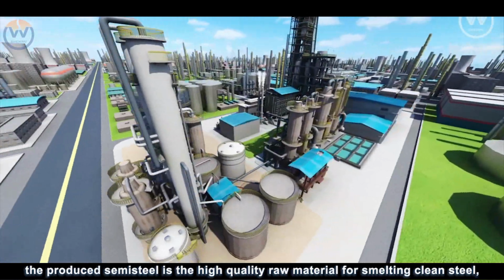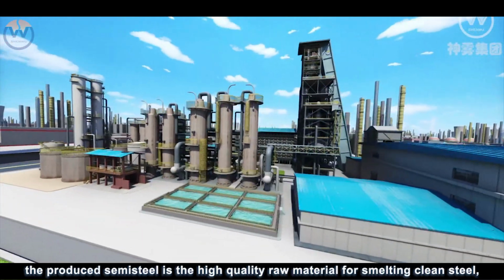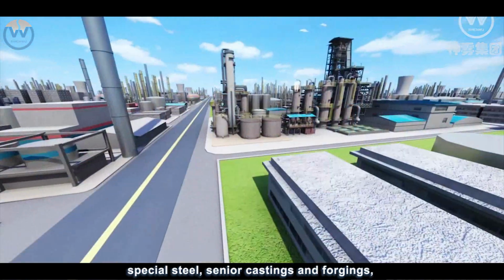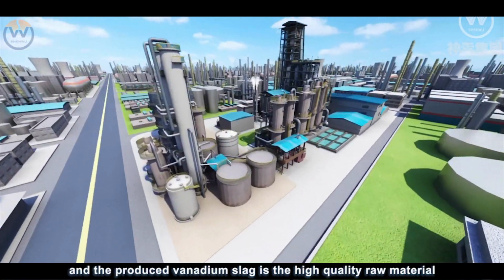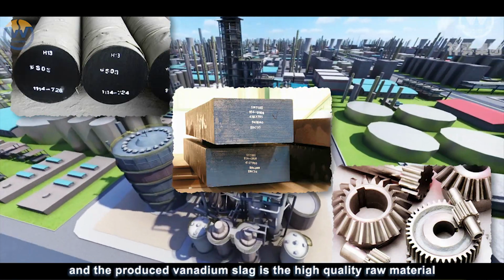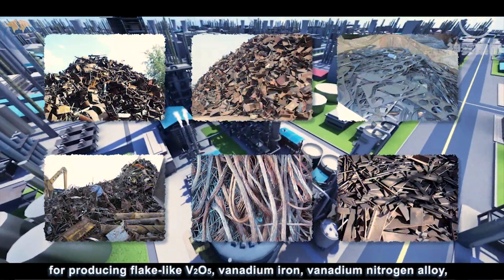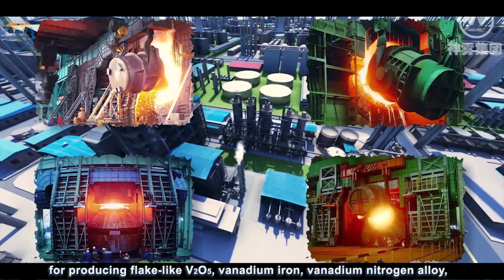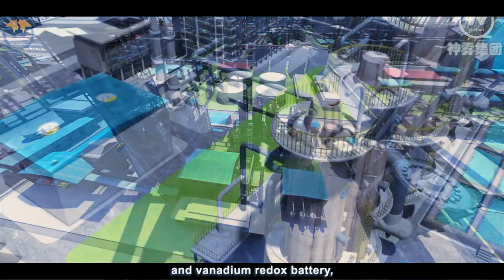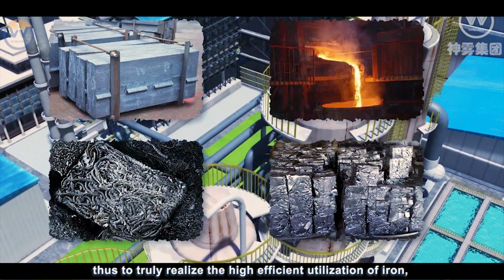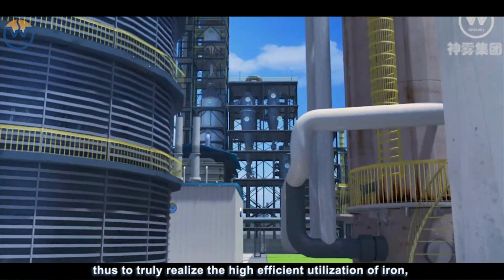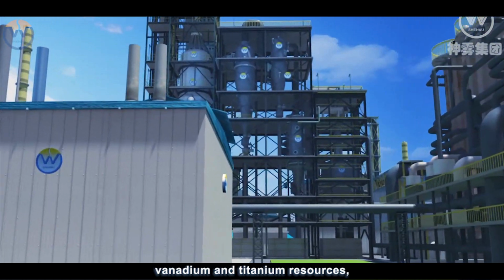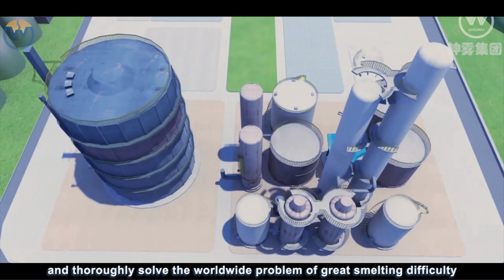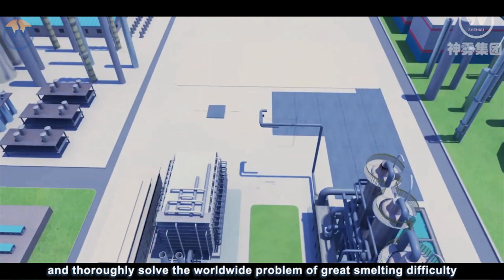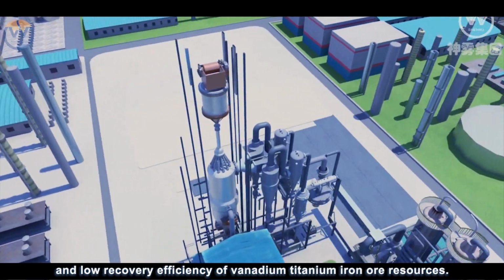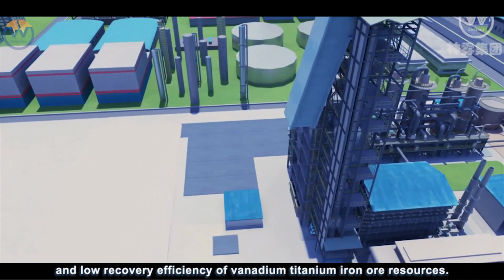The produced semi-steel is the high-quality raw material for smelting clean steel, special steel, senior castings and forgings, and the produced vanadium slag is the high-quality raw material for producing flake-like V2O5, vanadium iron, vanadium nitrogen alloy, and vanadium redox battery. Thus, to truly realize the high-efficient utilization of iron, vanadium, and titanium resources, and thoroughly solve the worldwide problem of great smelting difficulty and low recovery efficiency of vanadium, titanium, iron ore resources.